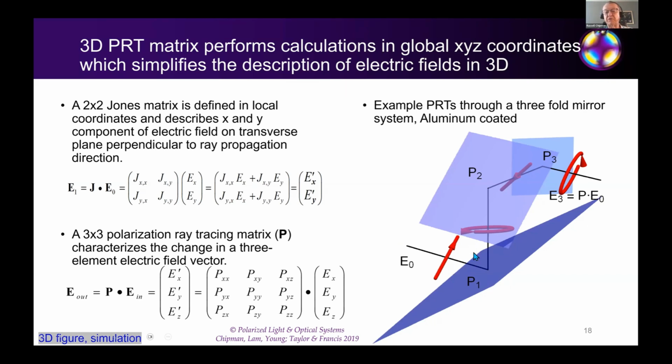Here we can see that 45-degree polarized light becomes elliptically polarized by the retardance of an aluminum mirror. Its axis is also rotated a little by the diattenuation. But here, if the second mirror is at the exact same angle, these will cancel for that one on-axis ray. So it's back to 45 degrees. Then the third mirror converts it back to elliptically polarized light again. And so I can write a Jones matrix for these 3 and keep track of the coordinate changes.